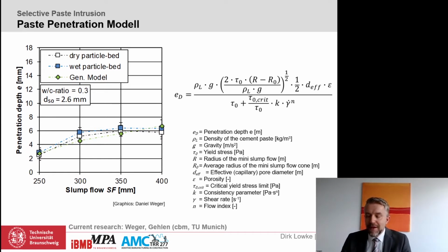Furthermore, his model considers the horizontal flow of the cement paste. By doing so, the model is able to predict the penetration quite accurately, as you can see by comparing, for instance, the green symbols with the white ones. If you're interested in further insights on this topic, I recommend the PhD thesis of Daniel Weger, which will be available quite soon. Thank you, Professor Leuke.